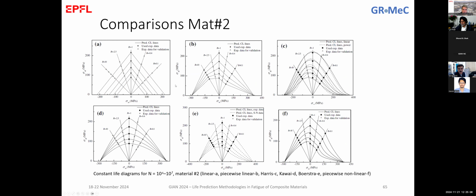So going to material number 2, again the same concept, using 3 SN curves to predict the other 2. Here you see the Harris diagram is much more stable than before. Piecewise linear is always accurate in our cases. The piecewise nonlinear is also accurate. Also Boerstra for this material seems to be stable. Even Kawai, the diagram from Kawai is more or less good, although it tends to overestimate the material behavior. The linear is again not good as we expect.